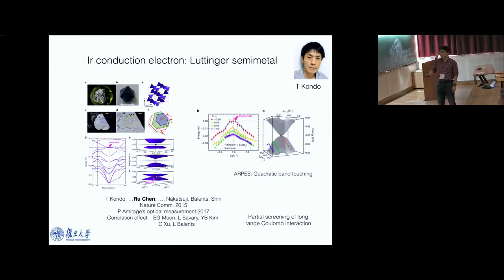Now many other people, like E.G. Moon, L. Savary, Yongbaek Kim and Chen Xu, studied the correlation effect, because if you tune the Fermi level right at this band touching point, the density of states is vanishing, because quadratic band touching in 3D has vanishing density of state. In 2 dimensions it has a constant density of state. So the Coulomb interaction is not completely screened. The Coulomb interaction is partially screened. That may lead to.